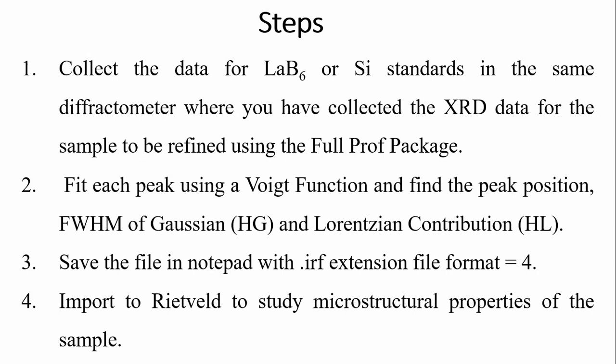Second, using the Voigt function, we will fit all the XRD peaks and find the peak position and FWHM contribution to the Gaussian and Lorentzian profiles, and then save the data to Notepad with the extension IRF file. This file format is type 4, and we import it to the Rietveld package to study the microstructural properties. Let's start how we do it.